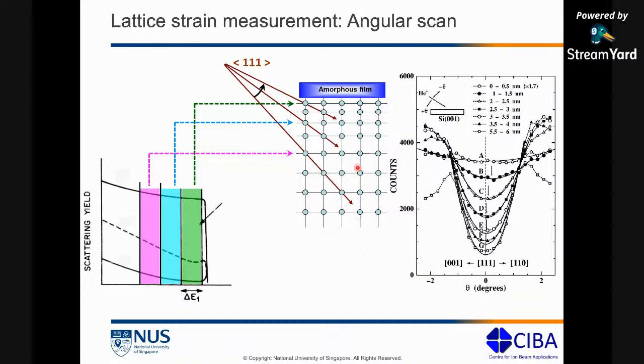Therefore, your counts are the lowest. You go up in counts, come to curve D. Now your counts are higher, which means the channeling is not very good. That means it is coming from somewhere in this part of your spectrum. This part corresponds to somewhere in this part of your sample, where now it is closer to the interface. It is slightly strained, and therefore your channeling is not good, and therefore your counts are also slightly